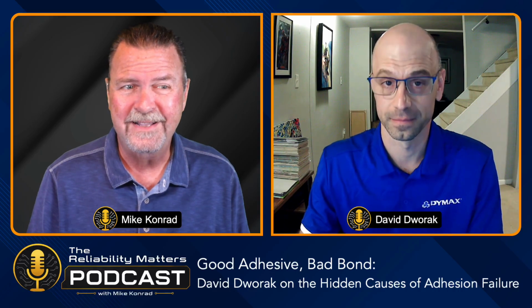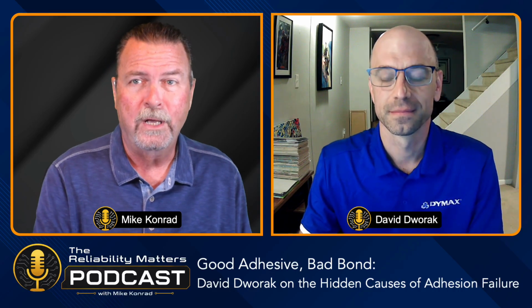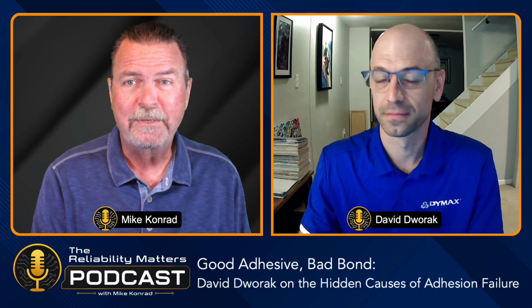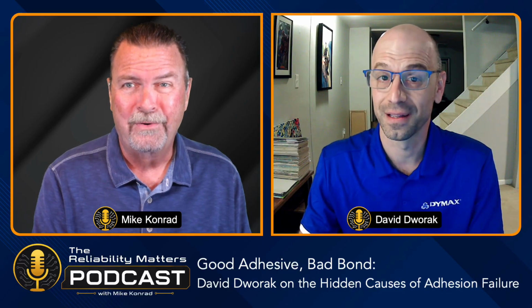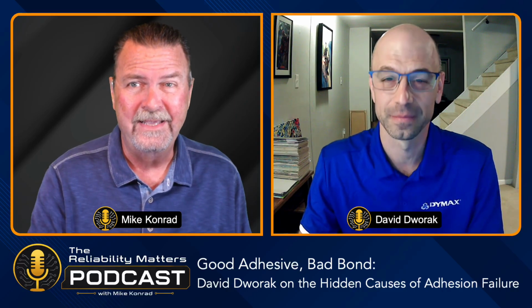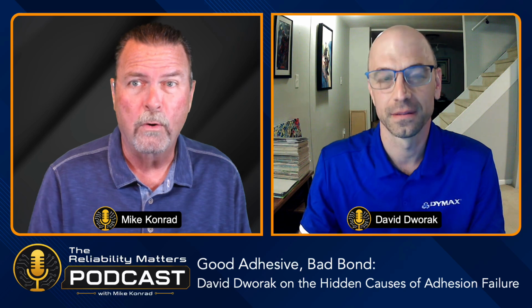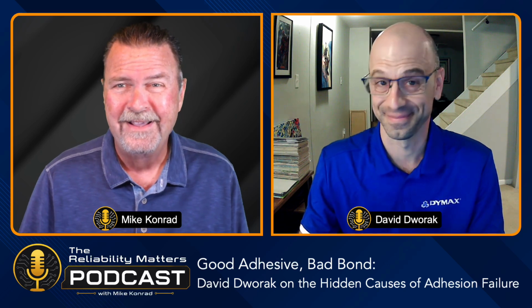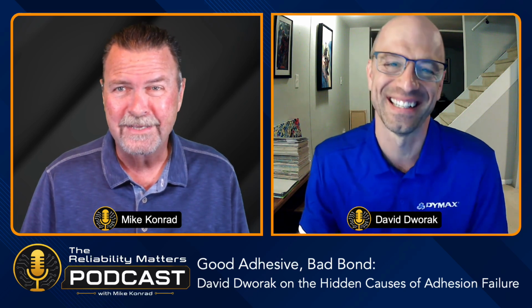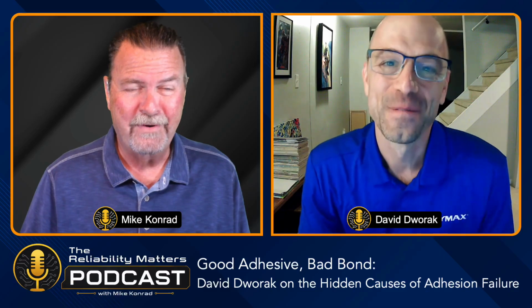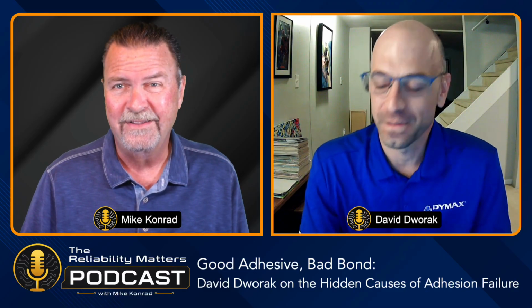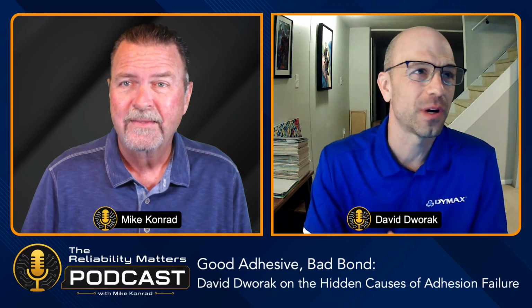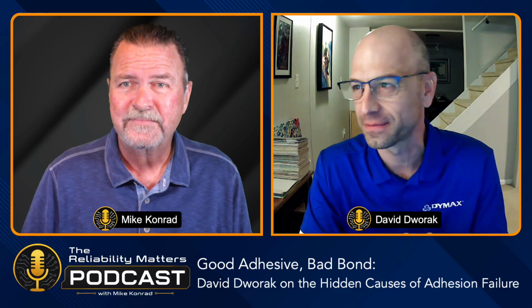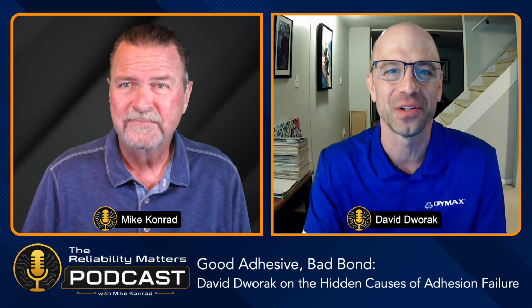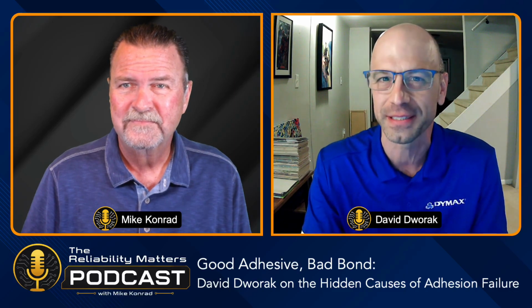Exactly. Because it's not so much the material below, although that does matter. It's what's between the material below and the adhesive above, right? It's an Oreo, so to speak. That white stuff in the middle that tastes so good may have a very low surface energy. And great analogy, that's why when you purchase an adhesive and you look in the instructions on how to use it, take a guess at what the first step is.